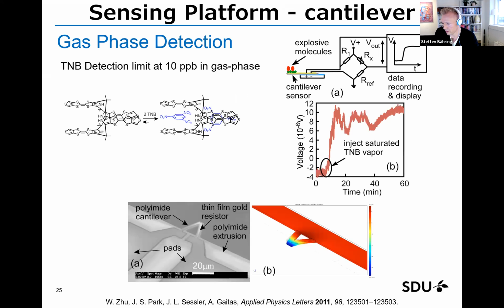So Sessler and co-workers reported in 2011 that the thiophene version of the TTF calix[4]pyrrole could be adsorbed onto this cantilever, and then by introducing TNB vapor, they were able to show a change in resistance. So saturated TNB vapor could show that they had a positive response. So this is one example.